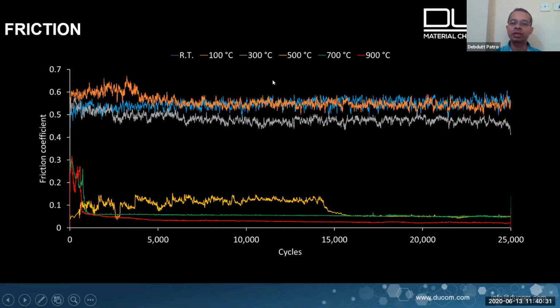As soon as you start increasing the temperatures beyond 300 up to 500 and 700 and 900, the coefficient of friction drops dramatically. From 0.5 to 0.6, it drops to 0.1. So these surfaces at high temperatures are less resistant to rubbing against each other.